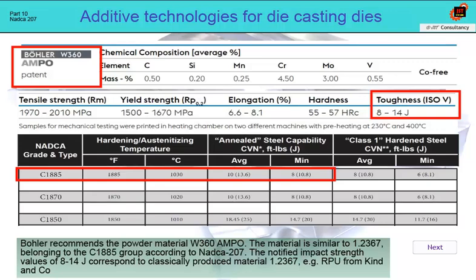It means after hardening in oil. However, since we do not examine input properties in 3D printing, but print finished parts directly, the values of 10.8 and 8.1 joules after hardening for classically produced steel are worse than the values reported for powder steel. That is very optimistic. However, the Böhler Company does not publish the printing parameters, nor if it has applied hot isostatic pressing technology, so it is up to the user to verify and confirm the printing parameters themselves.